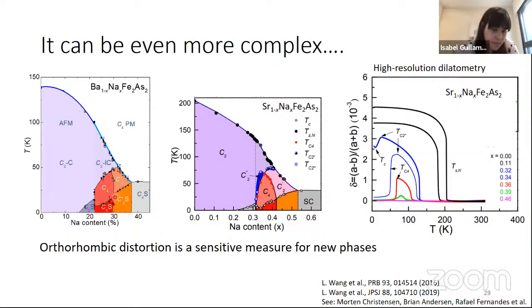What you can learn is that the C4 phase is the worst, so option 2 is the worst. The next worst is the spin vortex crystal, and the best is still the stripe phase. In this work, it was related to entropy changes and how much density of states is removed. Maybe you can look it up, there's a reference down here. This is very impressive work and a very interesting, complex material. So many phases. I think there is a lot to be done still, also quite intimidating, but there is a lot to be done there.